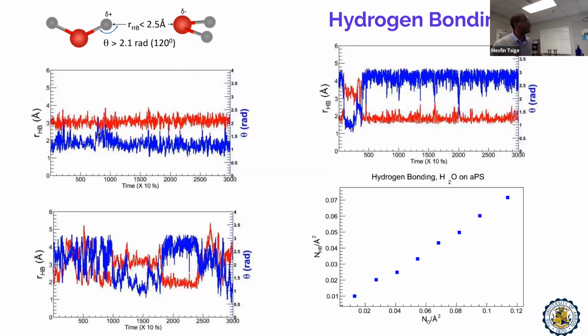Here I'm showing you 3 representative cases. The red one shows the distance between O and H. The blue shows the angle. Let's say a water molecule coming in close proximity with a surface oxygen, but not within this geometric condition that we put. The distance is slightly above 2.5, while the angle is really 120 degrees. And this water molecule may occasionally form hydrogen bonding, but it breaks quickly. We have also other water molecules. They don't form, then form, break. That happens much faster than the 20 picosecond that I talked about. We have also water molecules. They form, break, and pretty much form again and stay for a long time. So we have a distribution of lifetime of hydrogen bondings that happen at the surface.